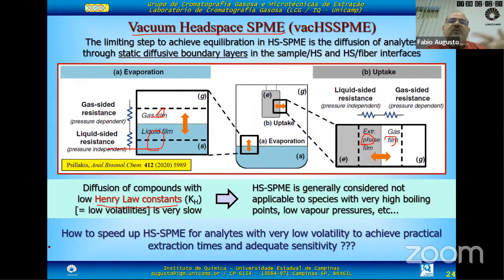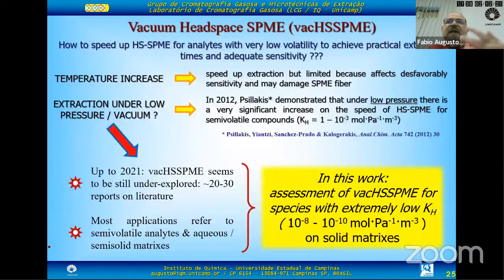How to speed up the mass transfer process to extend the technique to very heavy molecules? You can increase the temperature of operation, which is limited because you can damage your fiber, and you can have effects on the equilibrium position of the extraction process. The increase is limited. Also, you can perform your extraction under very low pressure, a vacuum. If you perform your extraction under vacuum conditions, the process of mass transfer from the sample to the fiber is very, very accelerated. And they demonstrated that in practice in 2012, the paper is here.